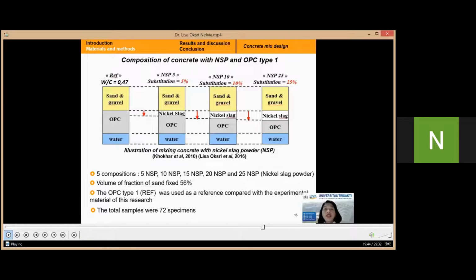The compressive specimens were made by gradually substituting the mass of cement by the nickel slag powder from 0% to 25%. For this experiment, the total was 72 specimens. The water to cement and NSP ratio is constant, and the water and the paste volume were constant. Compressive strength was tested at the ages of 3, 7, 14, and 28 days.